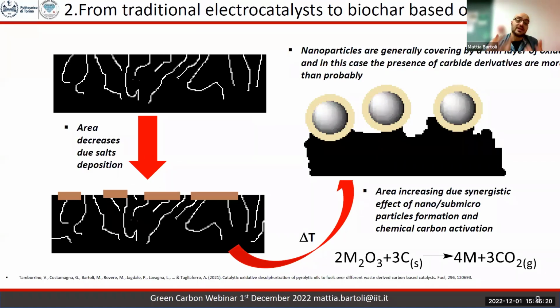So we increase the surface area. We remove a part of the less graphitized carbon, so we boost up the conductivity of the material. We tailor it with an inorganic structure that is able to promote catalytic activity, and we try to match the properties of an electrocatalyst, keeping also an eye on the sustainability of the process. Because what we really try to do is just produce a catalyst that is green and sustainable. And that's the reason why we stressed the biochar component of our research, but that can also perform as the more advanced materials.